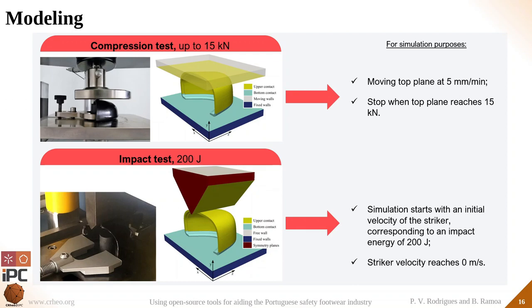For modeling purposes, in the compression test, we imposed a fixed displacement at the top plane of 5 mm per minute and an ending criterion of 15 kN force. At the impact test, in order to have an impact energy of 200 joules, we took into consideration the weight of the striker and we adjusted the speed accordingly. The simulation was stopped after the striker reached a velocity of 0 meters per second.